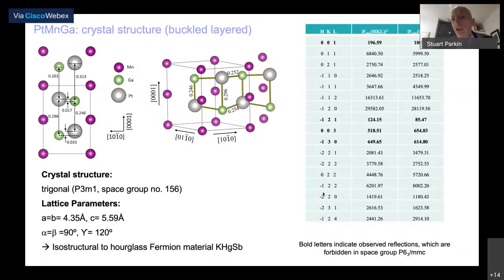But I wanted to finally mention there is another compound which we've recently discovered in which we can see a closely related property. It's a totally different structure. It's a layered structure, platinum, manganese, gallium. It has a perpendicular magnetization. And we discovered that the structure in the literature is wrong. It's broken. It's not a centrosymmetric structure, and therefore it actually has a very interesting layered structure consisting of